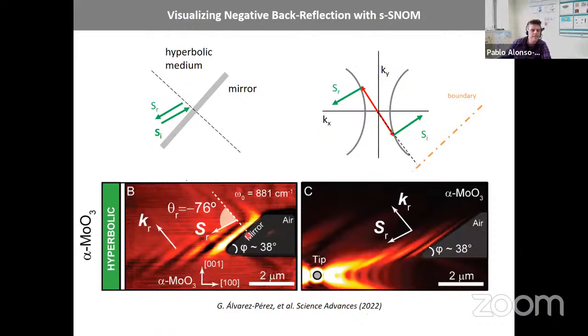Well, this is the result. So we have the same mirror, and now instead of having this energy going in this direction, we have K going in that direction, but S, you can see here the energy, because the fringes go in that direction, is going here. And this is exactly what we expected from this sketch that I did before. So the back reflection from this mirror is like this.